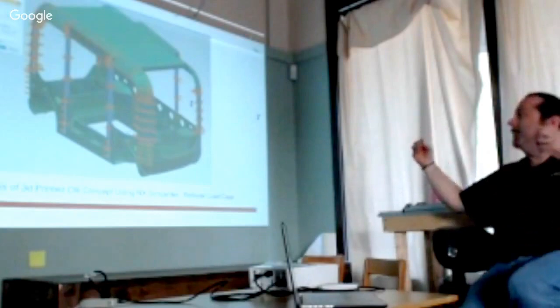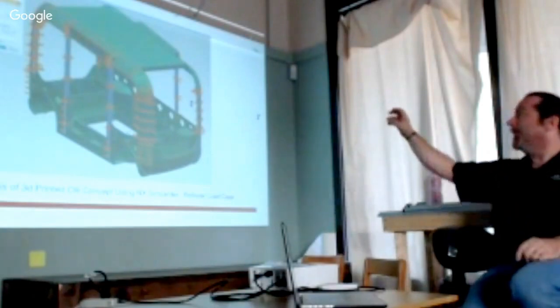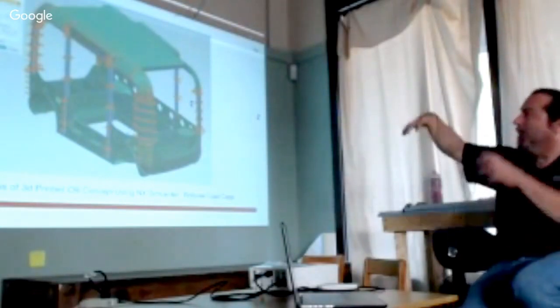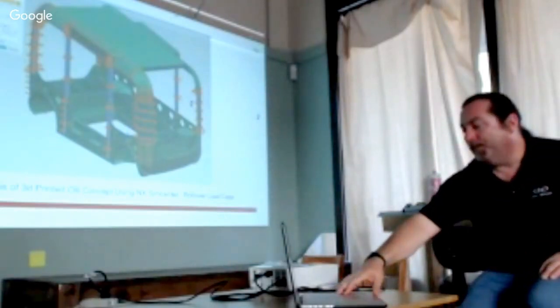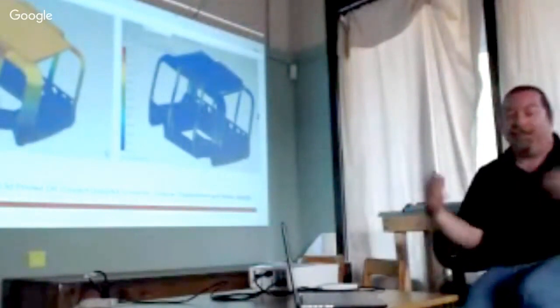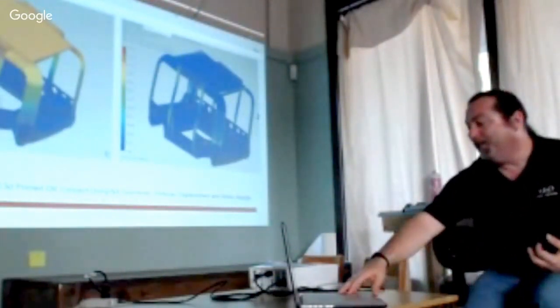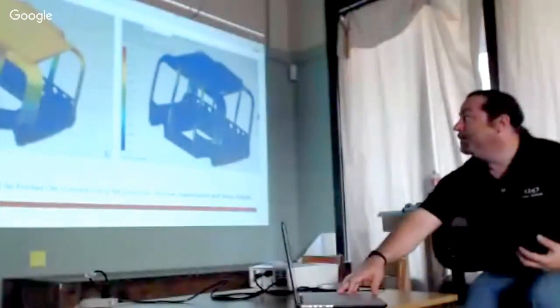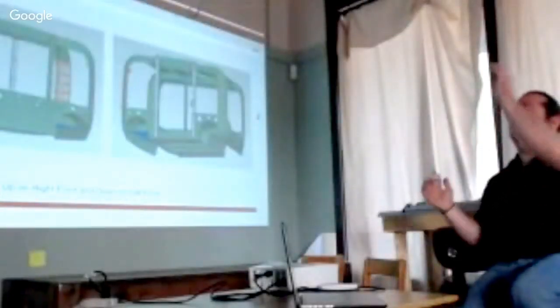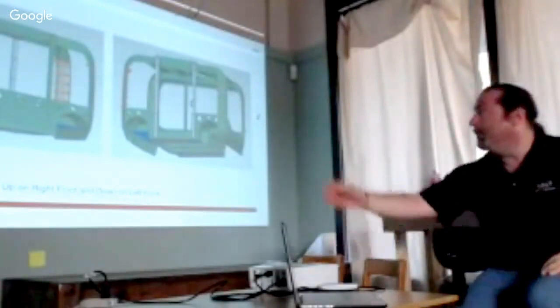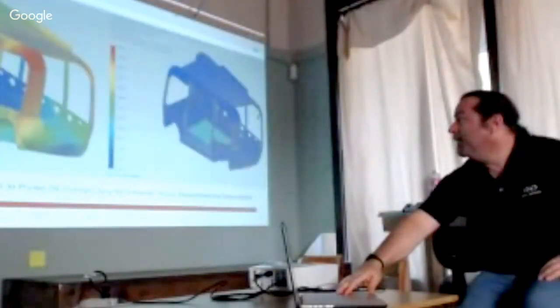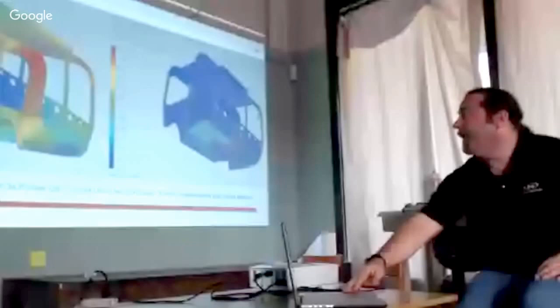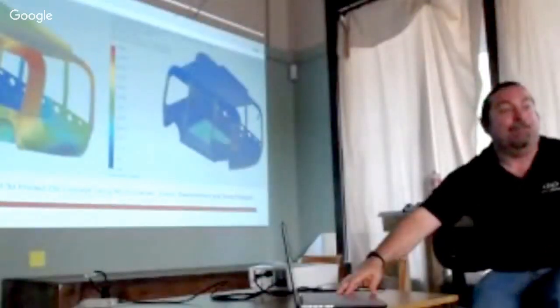The gold arrows are the automatic surface or contact pairing. There are bonded composite corner sections connecting the upper and lower printed chassis, and then aluminum tubes. There are 4 aluminum tubes in the center. This was really a quick check to see if it's going to hold together. It has a chance of passing rollover, and it did pretty well. But it's by no means a complete stress analysis. And then this is the torsion, where I'm applying 6,000 pounds on each front corner and constraining the back section. That also had more than adequate torsional rigidity for driving loads.